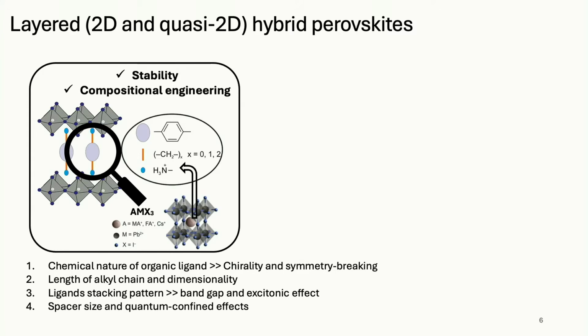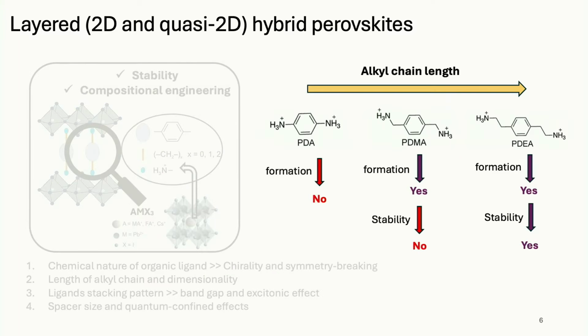So this is just kind of a simple paradigm for you to start to think about how these materials are assembled. You imagine you have the reagents to make the hybrid perovskites, such as lead ions and methylammonium, these small A cations. But then you say, what should I put for my spacer layer? It turns out that materials with at least one benzene ring are much more hydrophobic or seem to promote stability better than the pure alkyl ones. So we'll say there's a benzene in there.